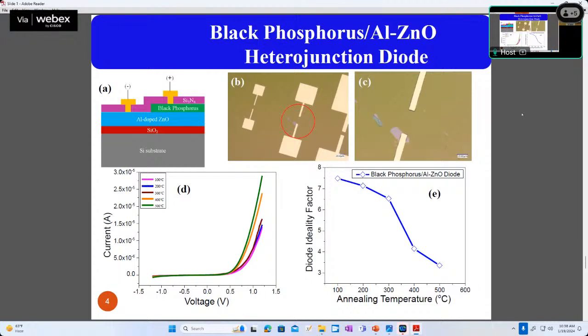To check the quality of a diode, there is a parameter to indicate the quality of the diode, that is the ideality factor. Okay, so that we have calculated, and we found that if the temperature is increasing, the diode ideality factor decreases. Here for silicon nitride passivation, it was around 3, and for a typical silicon diode we have an ideality factor in the range of 1 to 2. Okay, so it has that much quality like a silicon diode, but it can operate up to 500 degrees centigrade, this diode.